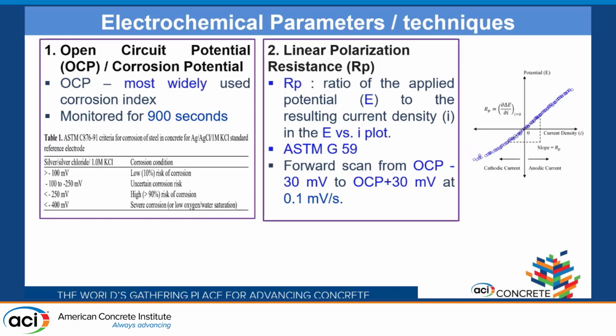So we have used 3 different electrochemical techniques to get insight into the corrosion activity in alkali-activated concrete. First one is open circuit potential, or the corrosion potential, when there is no current flowing in the system. What is the potential there? This is one of the most widely used corrosion indices. However, the ASTM limit for OPC based binder specifies that any OCP or open circuit potential below negative 250 millivolt would indicate that there is a high chance of corrosion in that system.